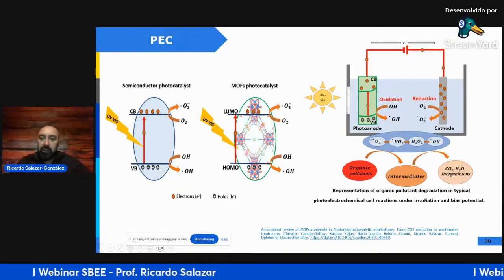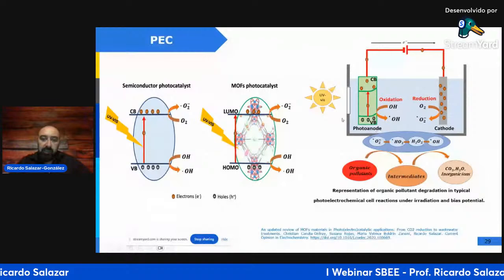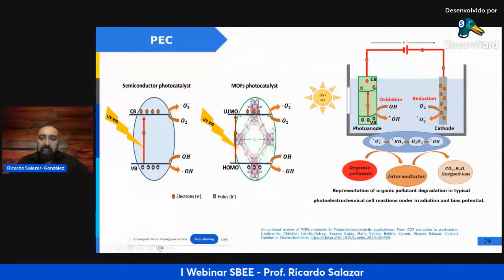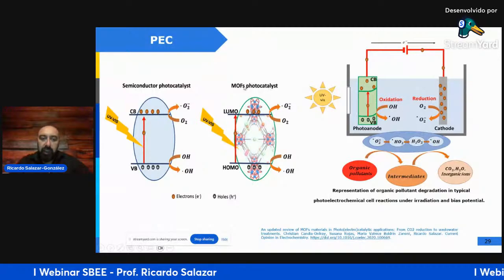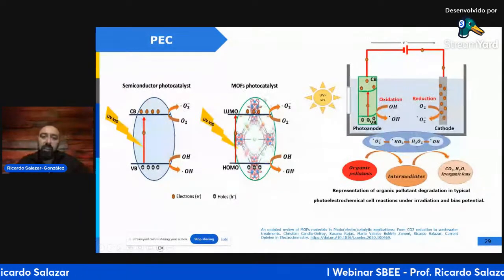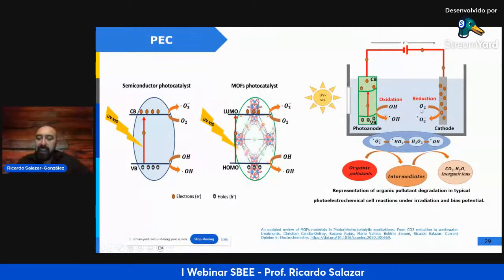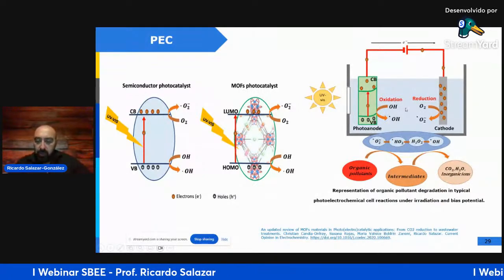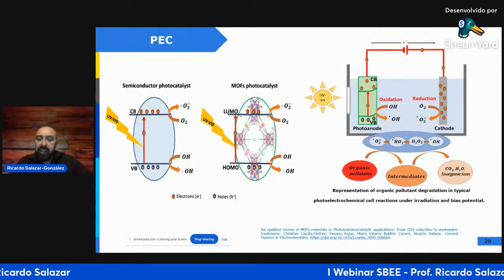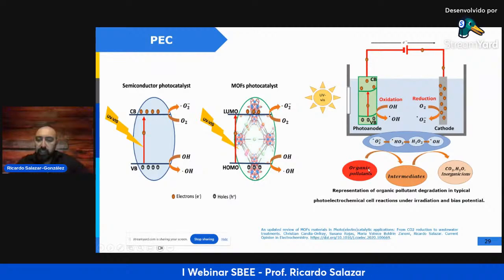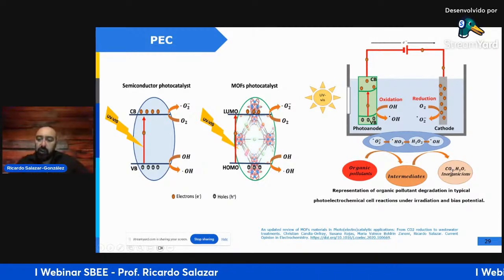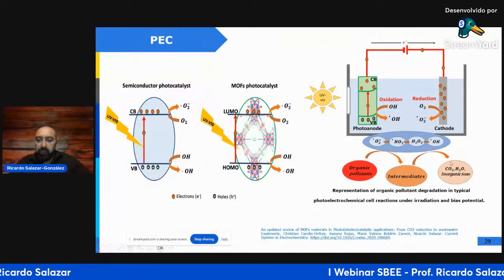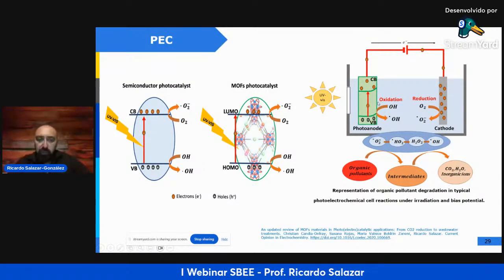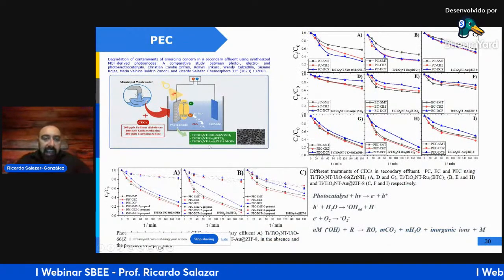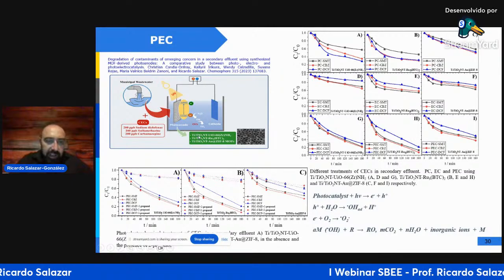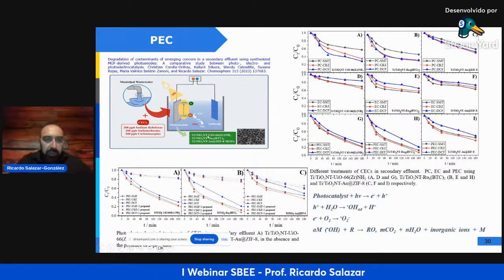And the work with Professor Maria Valnice Boldrin consists in the modification or generation of catalysts based on metal organic frameworks, different kinds of MOFs, and we treat real wastewater from a secondary effluent of a wastewater treatment plant. So we study the elimination or degradation of organic pollutants to produce carbon dioxide or final byproducts using different photocatalyst surfaces. In this work, we used 3 different photocatalysts based on MOF structures.